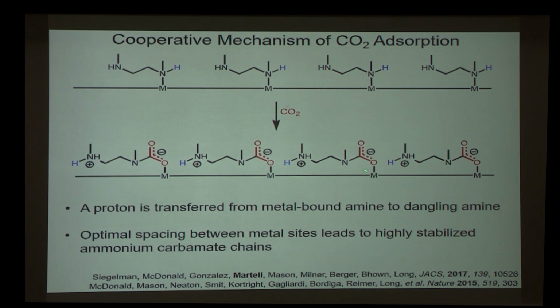And it is that perfect spacing between metal sites that underlies the cooperative mechanism. What happens when we capture the first CO2 molecule is it's not particularly favorable. We generate something charged that is not very stabilized. But capture of the first CO2 molecule makes capture at the neighboring site more favorable, because now we generate something charged that can be stabilized through ion pairing. And this effect is propagated to the third site and the fourth site and so on. And that's how the material can transition so abruptly from empty to completely full of CO2.